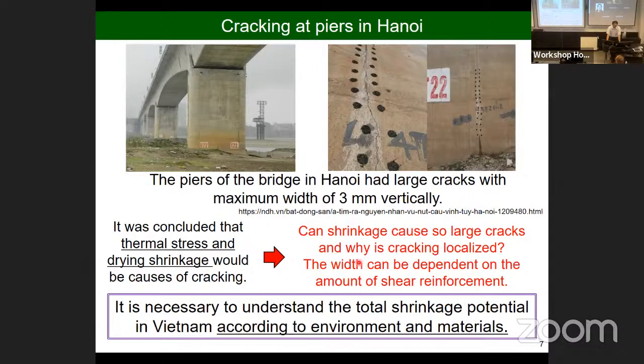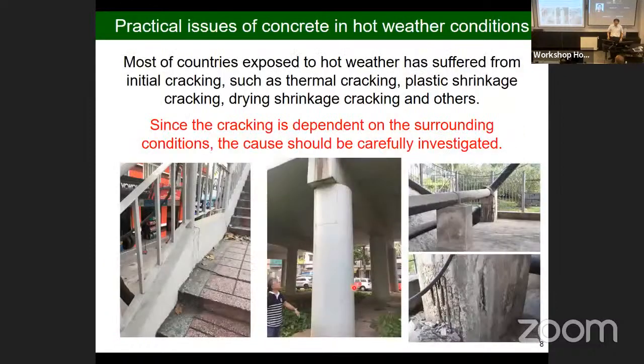Of course, in Vietnam there are no earthquakes. The reinforcement amount is different, but they don't know the shrinkage potential, how much concrete shrinks in Vietnam. And as Professor Maria pointed out, we don't know what kind of aggregate. We know the aggregate in Vietnam, but I don't know how much the shrinkage can scatter, as that depends on the aggregate. That is also a practical issue in Vietnam, but they don't know. They always say cracking is caused by drying shrinkage and improper curing. They don't understand the clear mechanism, the clear reason.